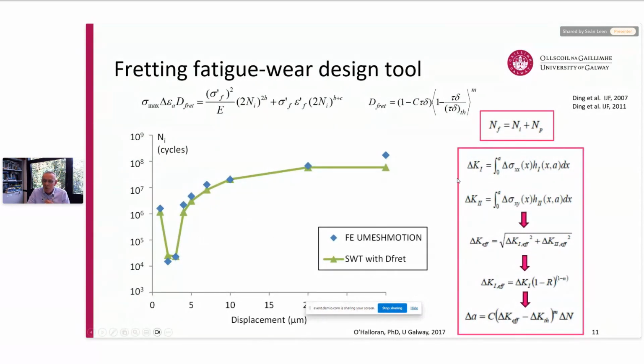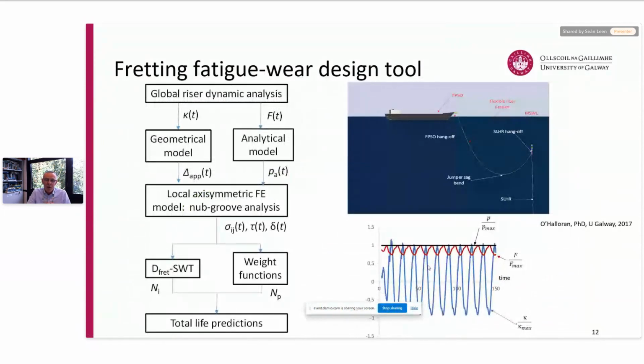And then typically we use that to predict crack initiation, as long as we use a scale consistent approach. But we've also included fracture mechanics with weight functions and mixed mode fracture, as you can see here on the right hand side, to include crack propagation. And what that allows us to do, as I'll show later, is to distinguish between crack initiation and total life. Then we've looked at real hydrodynamic models, and I won't show any simulations of the models here, I don't think, but you can see an image here of the kind of ship, and this is called a spar type arrangement for the flexible riser floating production system here, an FPSO type application.